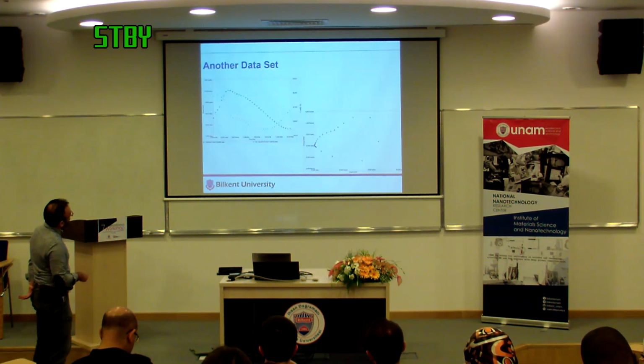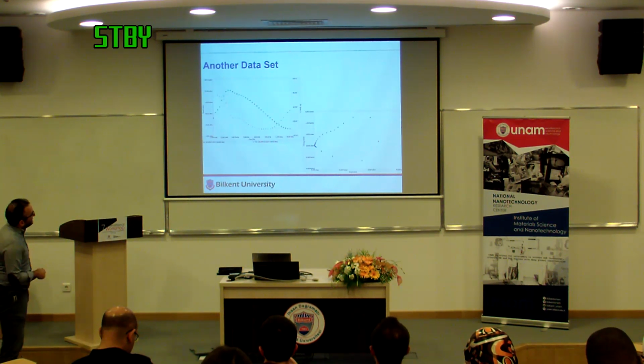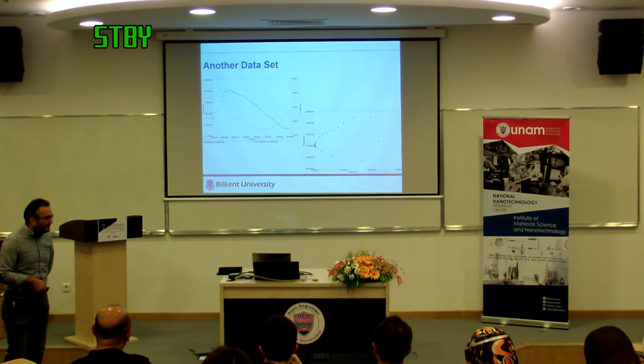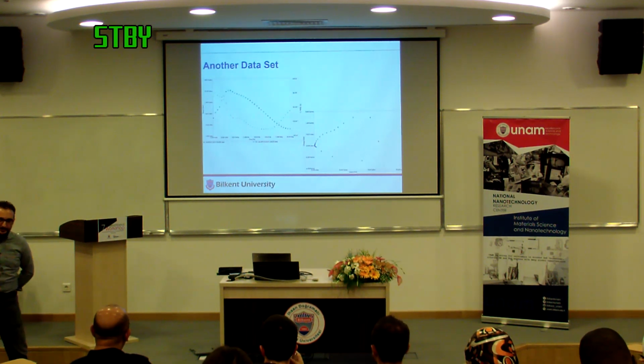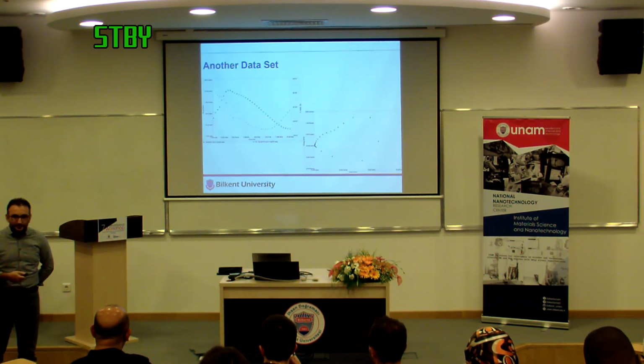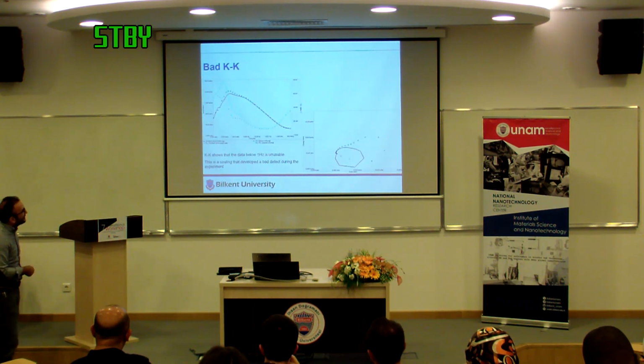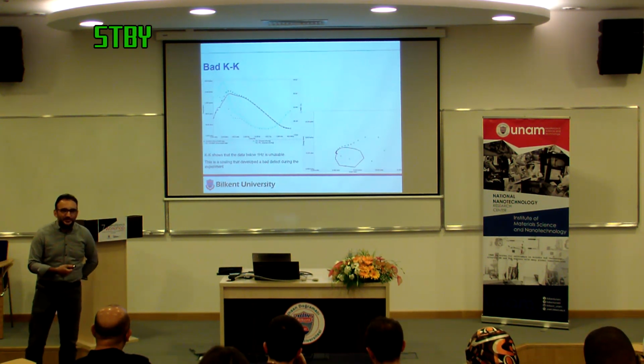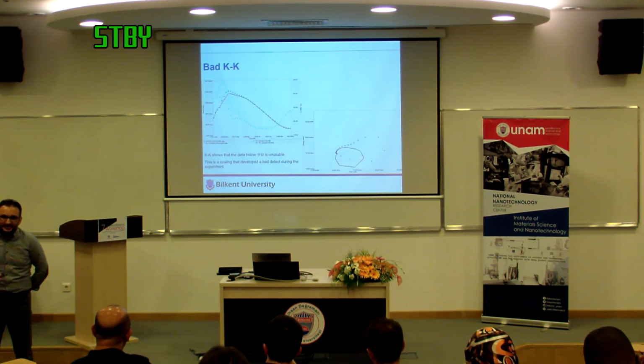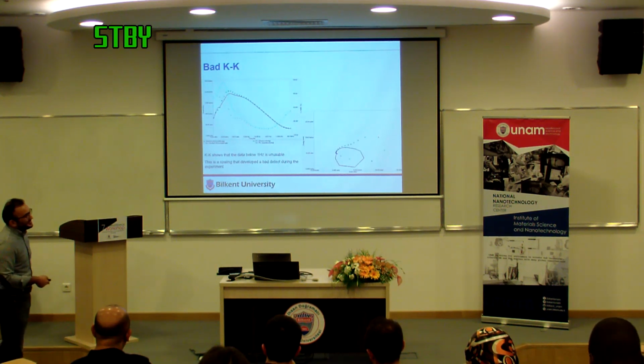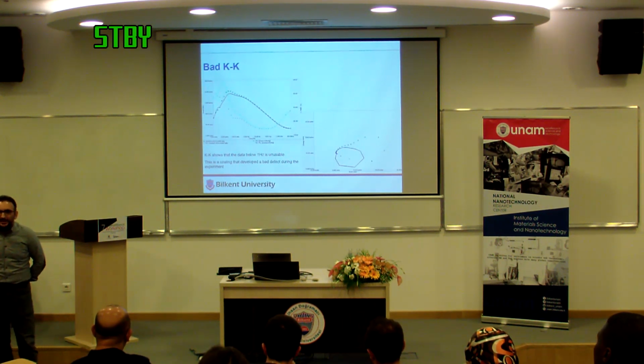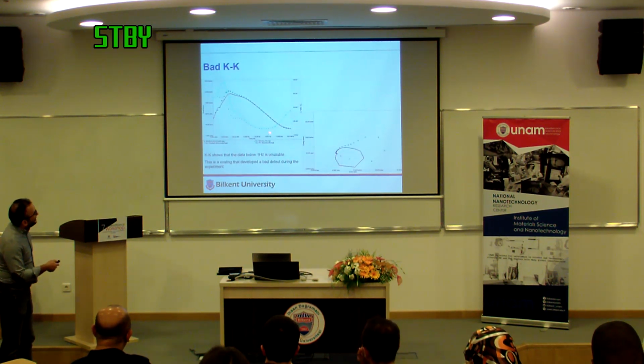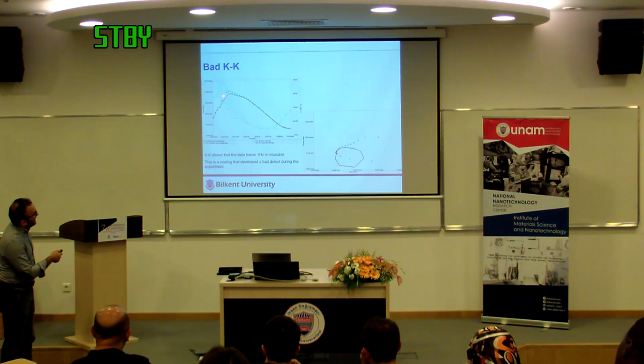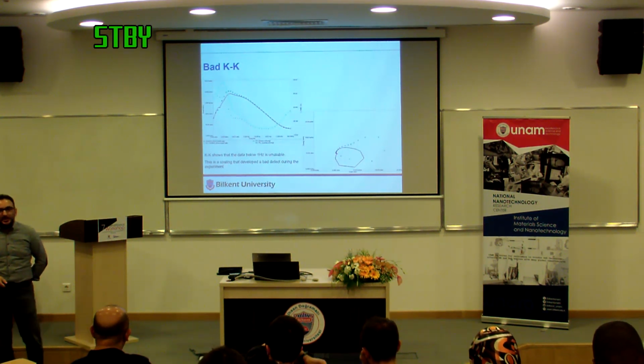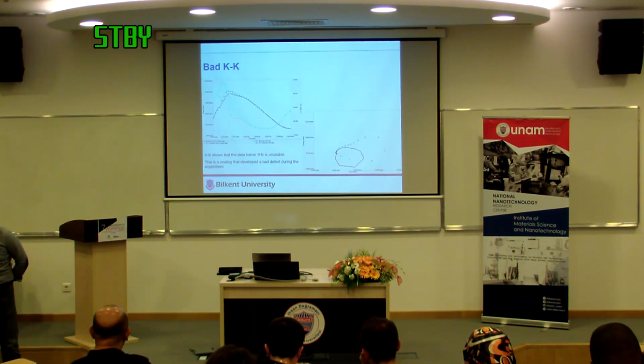Here's another data set. This is not something I took, but this was sent to me for help as I was working for an instrumentation company. And I, unfortunately, and I'm sad to say this, spent a couple of hours on this data before looking at the Kramers-Kronig transform. And the Kramers-Kronig transform is bad. So this data cannot be fit to any equivalent circuit model because it's not Kramers-Kronig transformable. It turns out this was actually a paint coating on some metal, and the paint coating broke down in the middle of the experiment. So the impedance was rising, and then it broke down, and the impedance started coming down. So there's no way to fit this data. This is not going to fit to anything because this is not stable.